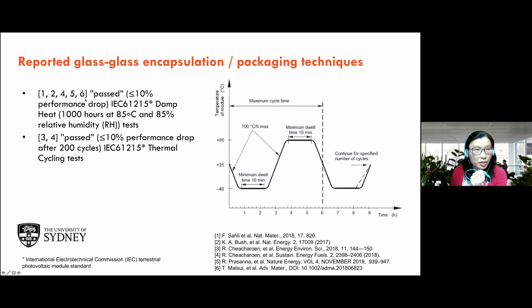So these 6 reports, they managed to pass, and I say quotation mark pass, because they managed to maintain a performance drop of no more than 10% after the IEC test. So the IEC standards have become stricter since. So you have to maintain 95% of the initial performance. For damp heat, it is after 1,000 hours of 85 degrees Celsius and 85% relative humidity. For the thermal cycling, it is 200 cycles between -40 and plus 85 degrees.